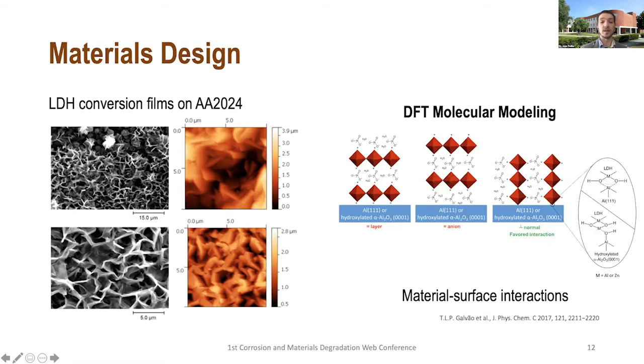Here we were using LDH, so layered double hydroxides, but as conversion films grown directly on aluminum alloy 2024. And we could see actually that the aluminum alloy had the plates of the LDH pointing normal to the substrate. And indeed, we found by DFT that the most favorable interactions between the LDH clusters and the surface was in the normal direction. So here we also have some sort of validation of how we could see the orientation of the plates and the whole crystallization process.